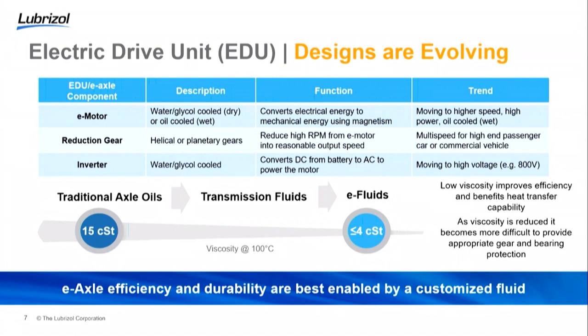Lower viscosity improves efficiency, and it also benefits the heat transfer capability, so taking the heat out of the unit. As you reduce the viscosity, it also becomes more difficult to deliver the appropriate gear and bearing protection. So really, it's about optimizing the chemistry so that you have optimized the viscosity and also still have the protection you need. We find that's best enabled by customized fluids.